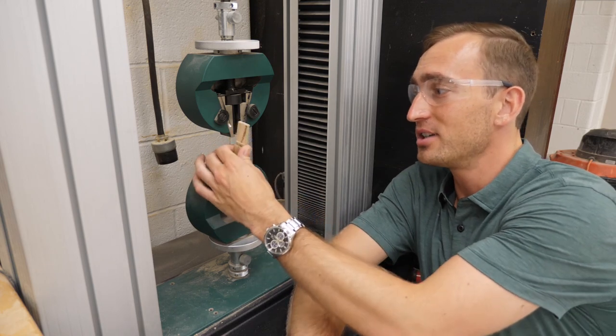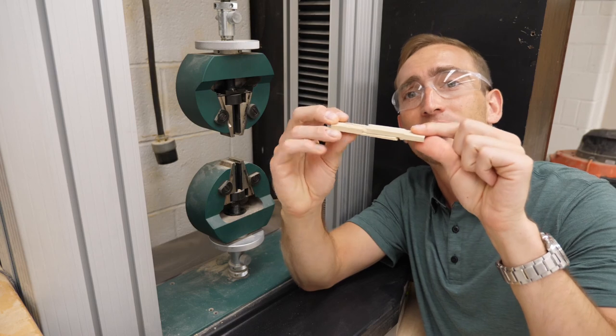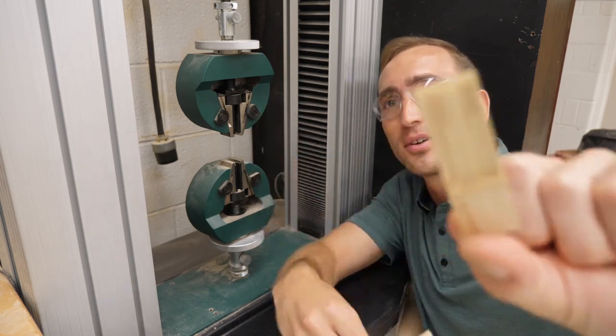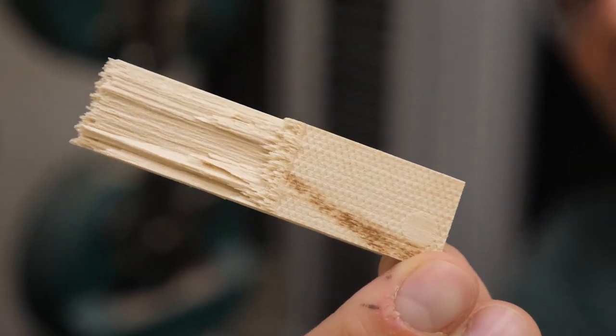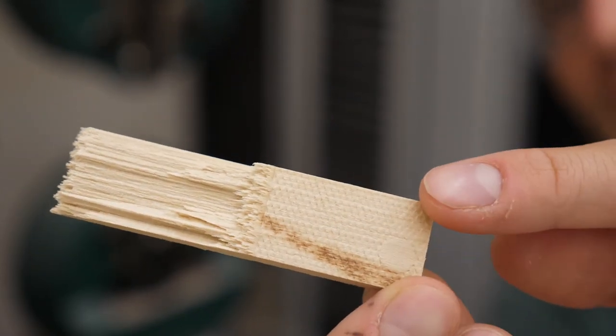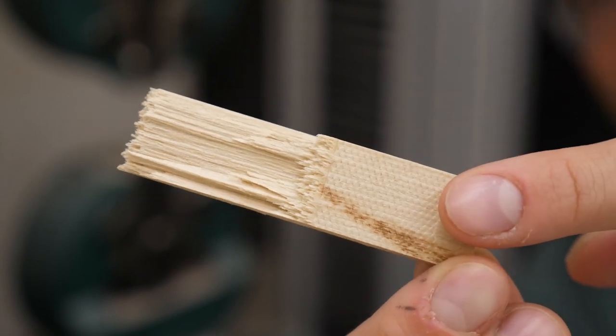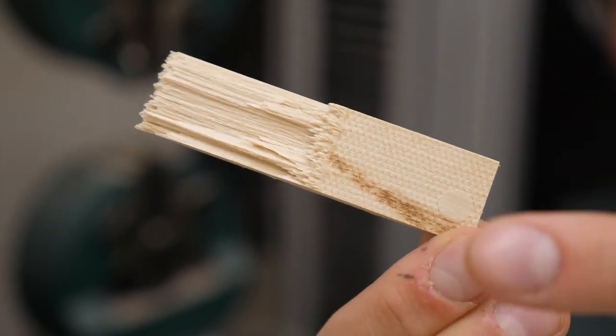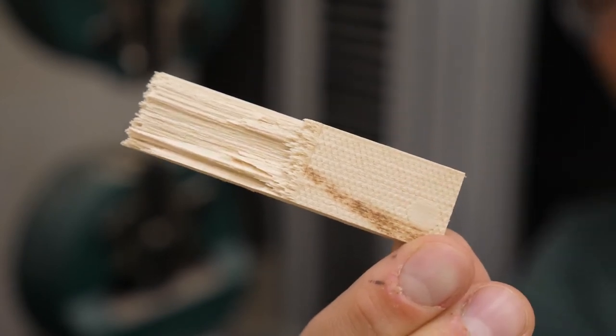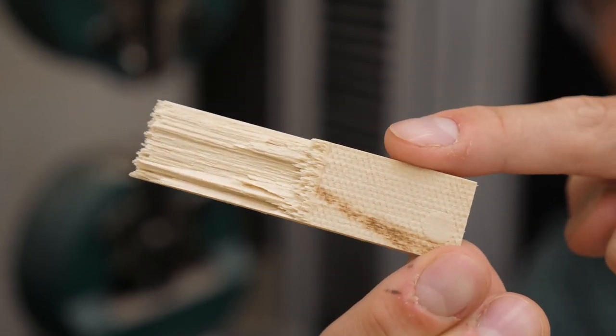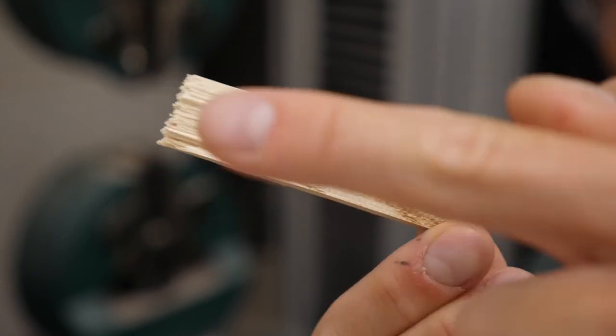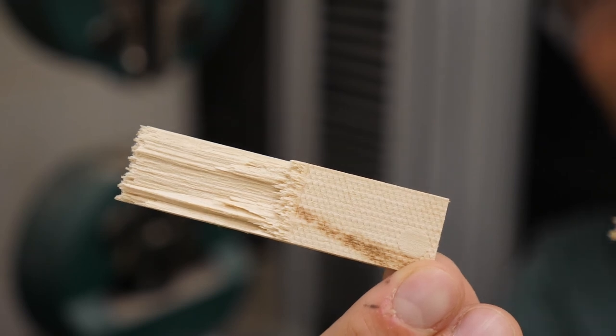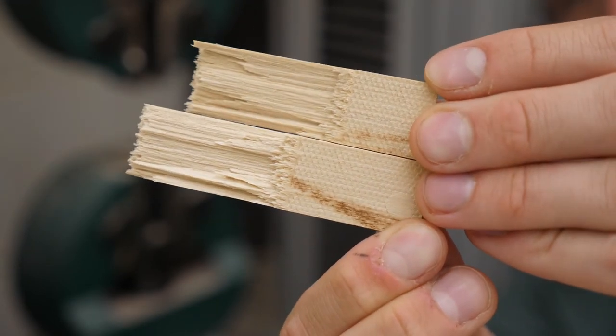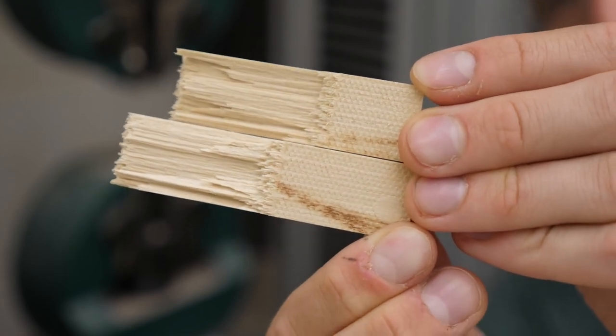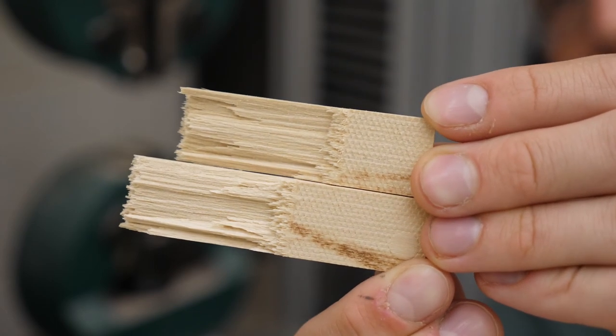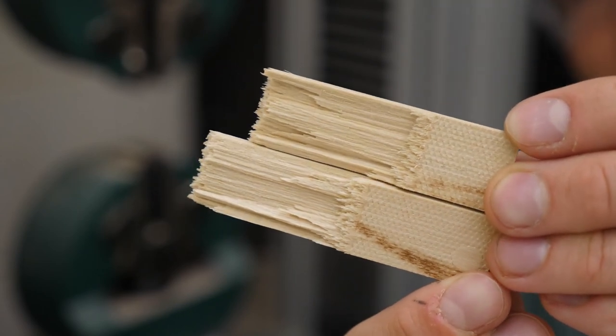Now, the way that you can see how this material failed is it's split right down the middle. And if I kind of can zoom this in here, so if you look at the wood specimen now, what you can see is, one, how many grip marks there are on the end conditions. This is why we have dog bone specimens, because you can see how tight the grips were on the ends. And what you can also see is that this wood was, because it was pulled along the grain, essentially just split and pulled all the fibers along relative to each other. And you can see that represented in this piece of wood right here. I could actually take these two pieces of wood pretty much and align them perfectly with each other, and you'd almost not be able to tell that the specimen even failed.